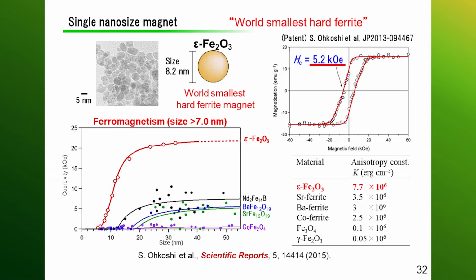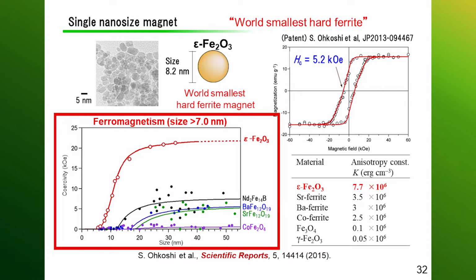There are 3 important numbers in properties of magnets. 3 kilo-Ørsted is the level of coercivity in ordinary magnets. Below this level, there is no more magnetic strength, so we need to break the barrier. The graph shows coercivity vertically and particle size horizontally. Compared to other ferrite magnets, epsilon iron oxide, Fe2O3, can maintain a very high level of ferromagnetism,